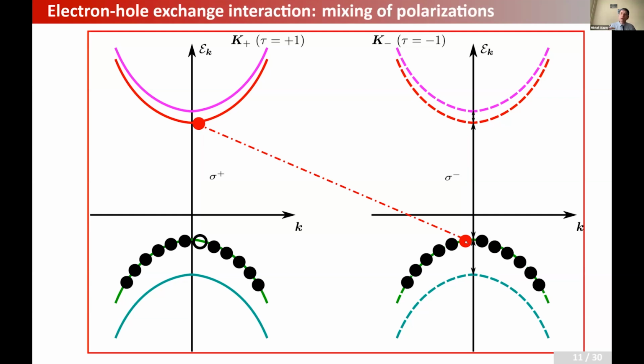But I will still take into account only the long-range part of the interaction, only the part that is related to large distances, many unit cells. So each electron remains in its own valley. We take into account this interaction, and actually the only process possible is the following. This electron from the conduction band goes back to the valence band, but the other electron in another valley gets promoted to the conduction band from the valence band. And so you see the valley has changed, and in this way, the valley flipped and the polarization changed.